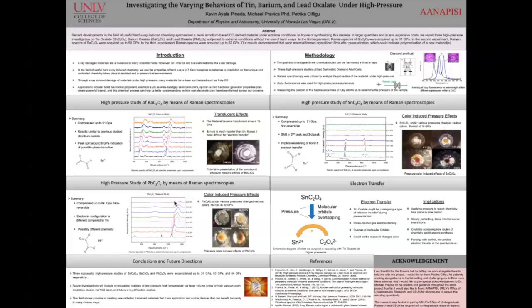Now, going into my last study with lead oxalate, the Raman spectra were a bit different compared to the tin, but it did also change color as tin did, but at a much higher pressure since we went up to 64 GPa here. And the differences in the Raman spectra could be due to the differences in the electronic configuration, or in other words, the molecular orbitals of this system here.